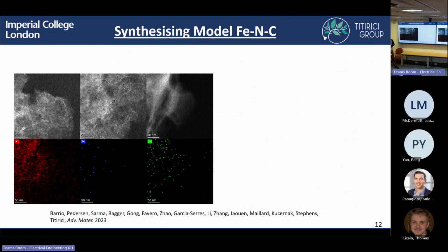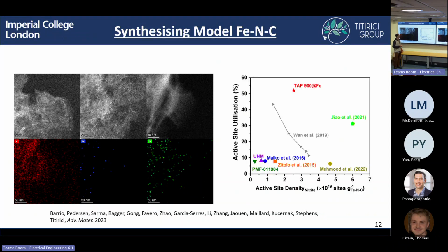And so this enabled us to develop, from the STEM imaging, we could see that we just end up with atomically dispersed species, confirming that we just don't have any nanoparticle formation. And in terms of the active site utilization, so we found when we compared to literature that we could obtain around 50% utilization of the active sites, which was above what was previously been recorded.